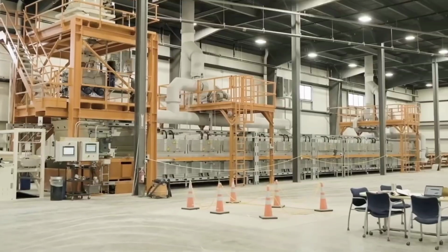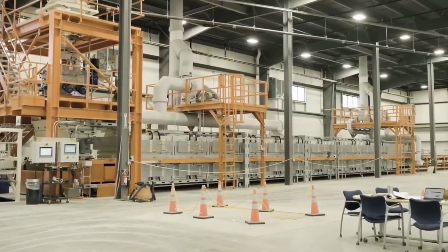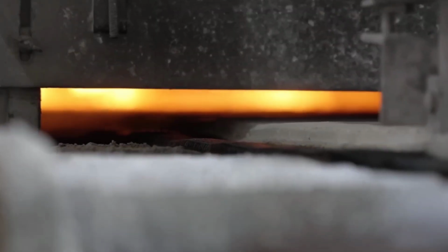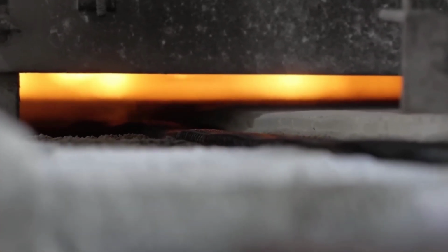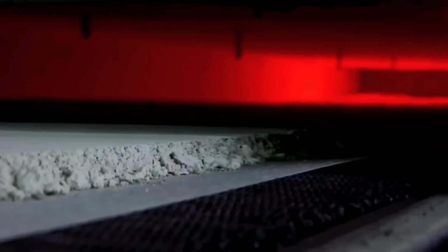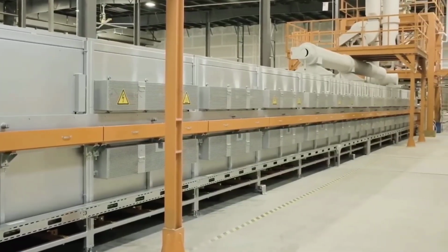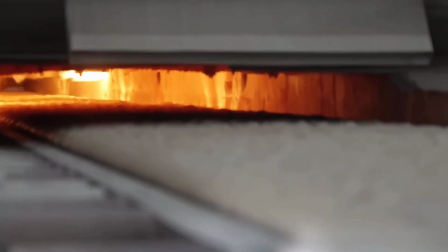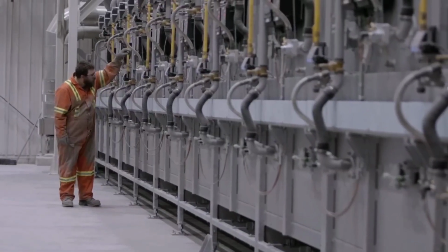As the material exits the rollers, it forms a stable, thin sheet that retains just enough moisture to hold the glass particles together. After drying, the blended layer is fed into a continuous furnace, a sealed system capable of maintaining extremely high temperatures and precisely controlling each stage of the material's transformation. Inside, the process occurs at roughly 1650 to 1800 degrees Fahrenheit, about 900 to 1000 degrees Celsius, hot enough to melt the glass but not so high that it destroys the foam structure.